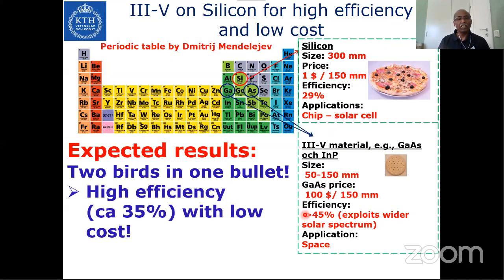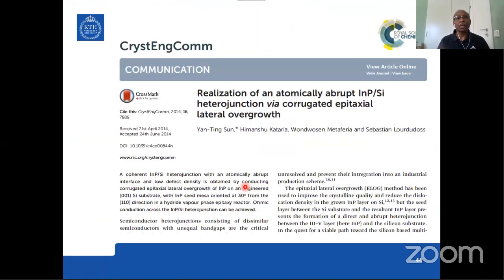So you can achieve high efficiency with low cost, because the substrate is a very high cost here, whereas the substrate is low cost here. So if you deposit on a large area on a low cost substrate, you can have a rather high efficiency. So this actually we try to do with a different technique, kind of modified the technology with ELOG, which we called corrugated epitaxial lateral overgrowth.